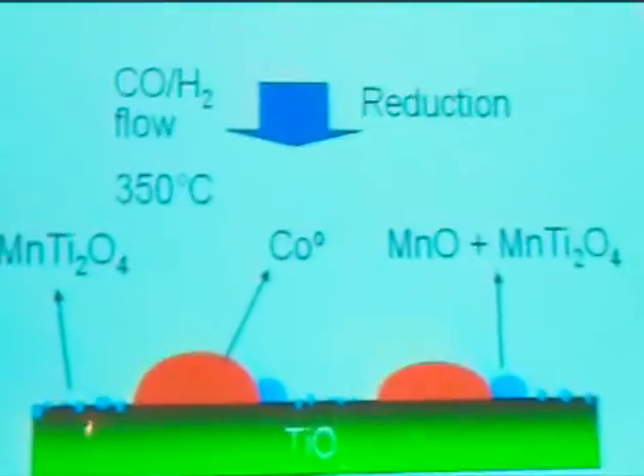If you would not have this manganese, we can prove with XPS that you have indeed reduction to TiO2-derived Ti3+, which then migrates onto the cobalt. If you have too much manganese, it also decorates the cobalt surface, decreasing hydrogen sorption. To summarize: after calcination you have cobalt-manganese and Co3O4 with manganese on the support; upon reduction or CO hydrogenation, you have cobalt metal with nearby manganese, and manganese titanate is formed. These structural features were also confirmed with XPS spectroscopy.